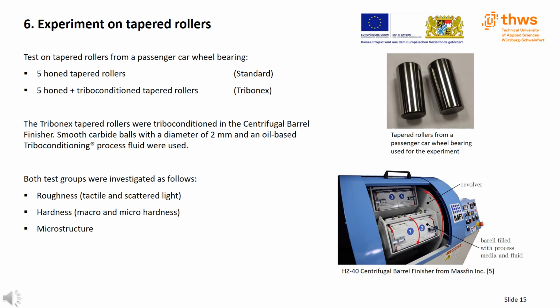The Tribonex tapered rollers were triboconditioned in the centrifugal barrel finisher shown in the bottom right. Smooth carbide balls with a diameter of 2 mm were used as the grinding medium. The process fluid that has been used is oil-based and contains tungsten and sulfur.